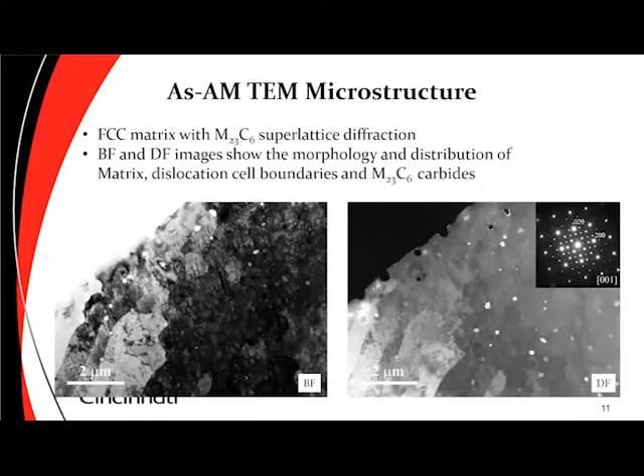When we look at the TEM images of the as-manufactured sample, it shows the matrix as FCC with, as you can see there, very high dislocation density, which is typical of the AM process due to its fast cooling process. Also, the images show carbides are distributed mostly at the cell boundaries.